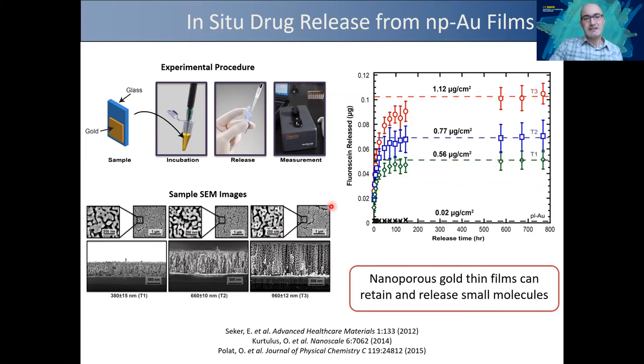But what's interesting here is that for a submicron film, these are thin films, from classical diffusion you would expect that all the fluorescein would be released in milliseconds. However, we are looking at half times on the order of almost a day and longer. So what's happening here is that this is no longer classical diffusion, but you have these nanotubes where a molecule traveling through that nanotube is seeing so much surface. As it sees the surface, it adsorbs, desorbs, diffuses a little bit, and then sees another surface and adsorbs and desorbs. This is hindering the diffusion. So it's really sustaining the release due to this surface adsorption-desorption mechanism, which creates a lot of opportunities for tuning the transport of the molecules, which I'll mention in a second.